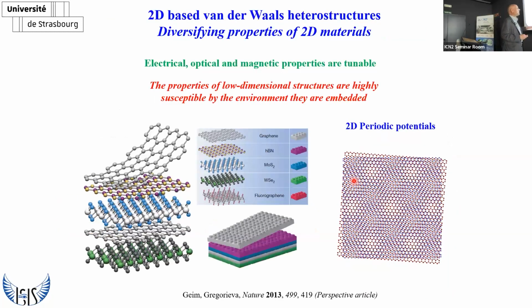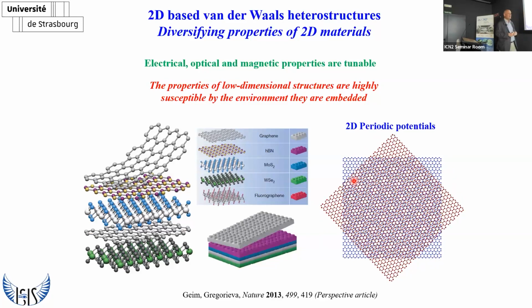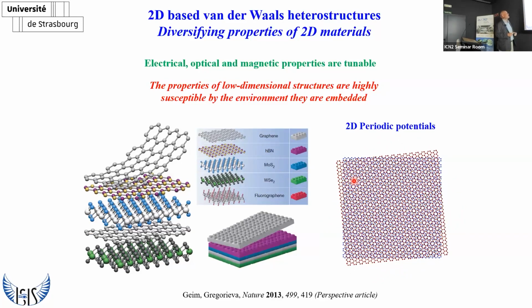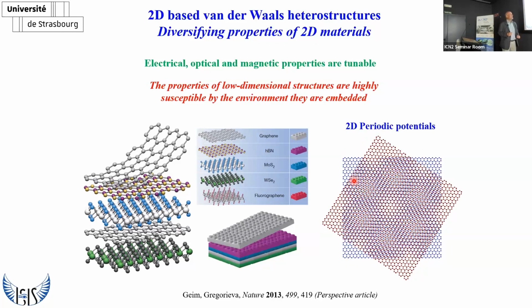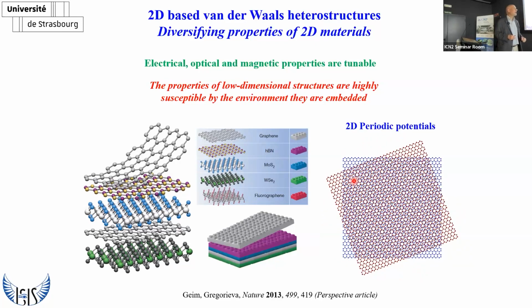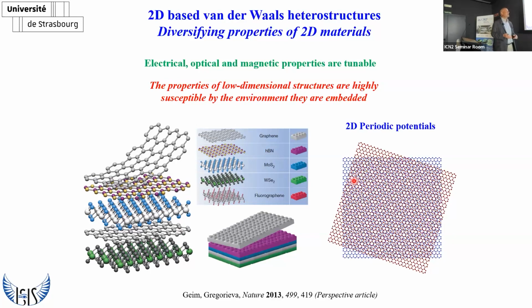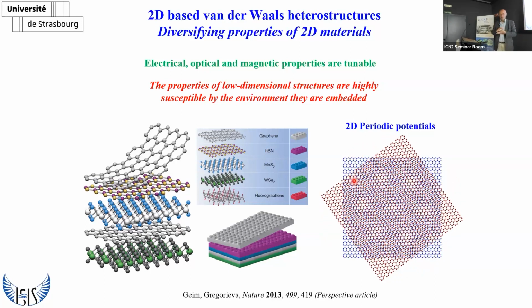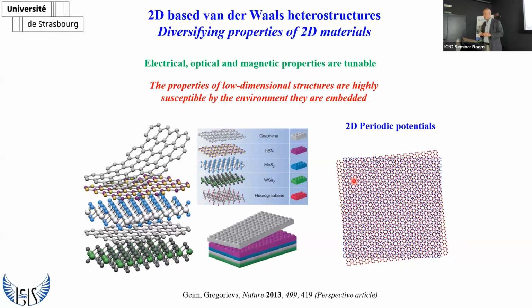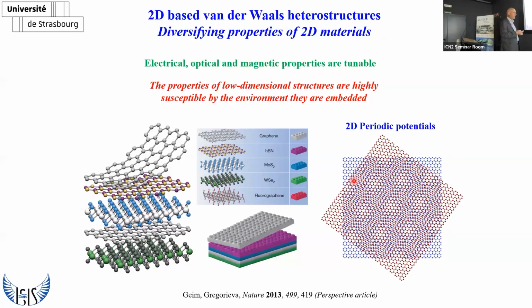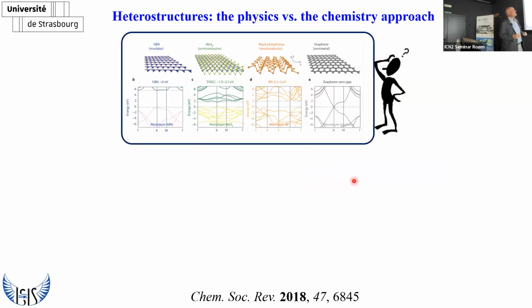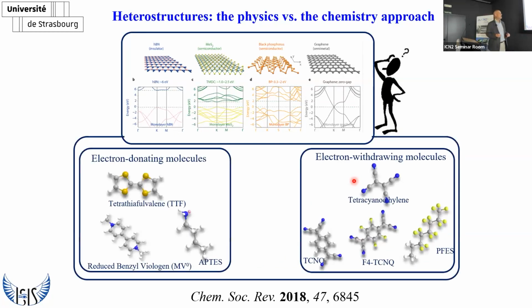interesting. Now, of course, our inspiration is the van der Waals heterostructure that has been reported thoroughly by a number of physicists, and actually the possibility of manipulating the properties, for example, by simply rotating one of the 2D materials on top of each other and developing 2D periodic potentials. Now, that is what a physicist would do. If a chemist instead, what they would typically do is take any kind of 2D material and literally throw on the surface of these 2D materials either an electron donating or electron withdrawing molecule and have a controlled doping effect.